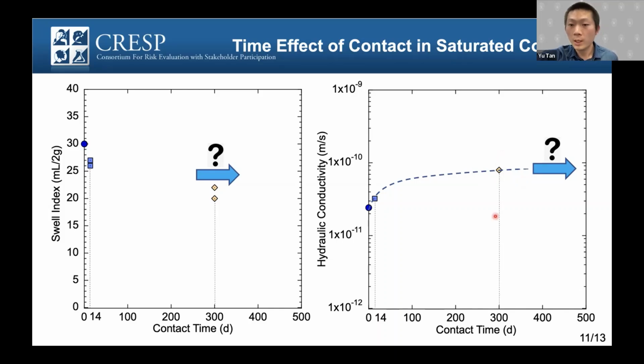Right now we only study for 300 days, about 1 year, but the lining system or the disposal unit is supposed to serve for 1,000 years. So what can we do to make a prediction or to estimate the performance of the liner in the disposal facilities? One thing that we can do is run more column tests in our lab to let them set for a longer time. And we can take the sample out at 1 year, 4 years, and 8 years, and measure the swell index and hydraulic conductivity to add more points in those two graphs and get a trend. We can estimate how it may happen in the future.